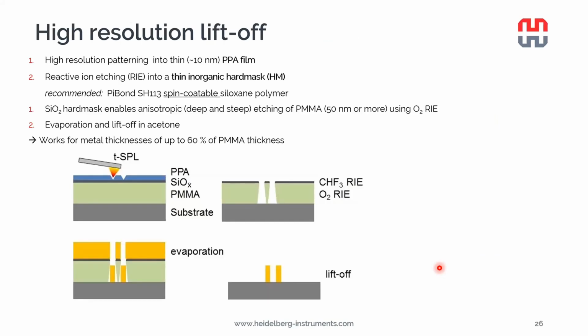I also want to mention quickly, as I referred before, we also have a process for transferring patterns that are less than 70 nanometers. And we call it, very originally, the high resolution lift-off process. Here, instead of 2 layers, we actually have 3 layers. So we have PMMA as the lift-off resist layer. On top of that, we spin coat a very thin layer of silicon hard mask.